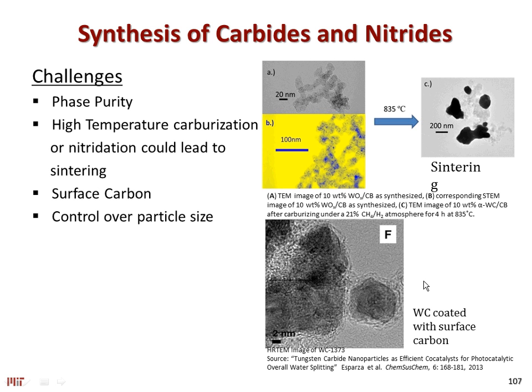From this path, we have seen that oxycarbohydrates or oxycarbides are important for this HDO chemistry. But independently, we have learned, for example, from Aditya Bhan's group in Minnesota that molybdenum carbide actually does this reaction very well at a slightly lower temperature. From Jingguang Chen's group, something similar. From the Hicks group at Notre Dame with phosphide, something very similar. So we're starting to converge on how these particular materials are excellent HDO catalysts that can perform these reactions under low conversion, under low hydrogen pressures.